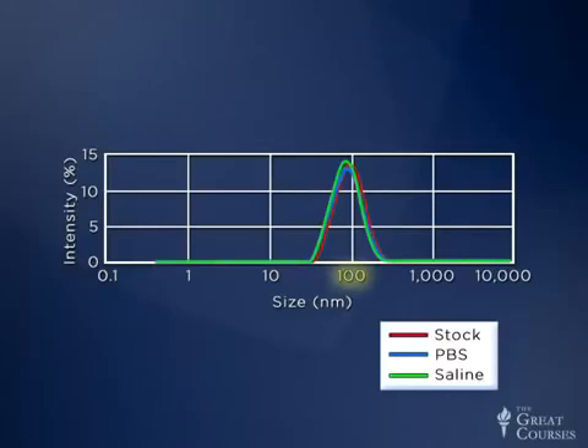with very little variability. At most, the particles varied in size by about a factor of 5, from the lowest size observed to the highest size observed. And when conventional gold seeds are used, their sizes can vary by a factor of 100. So we've cut down the variability in size quite a bit by using nanoscale gold.